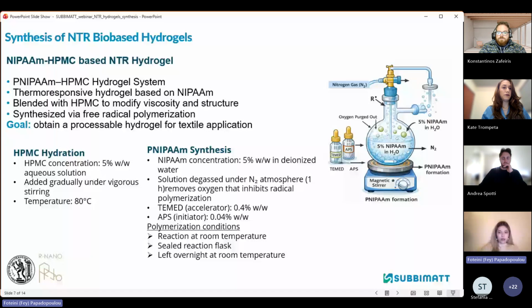Free radical polymerization forms the final network, and for this reason, we have APS as the initiator and TEMED as the accelerator. The initiator and the accelerator are vital because elevating the temperature above the NIPAM and HPMC transition temperature results in a collapsed polymer network that can't be further processed. So keeping the temperature low, room temperature ideally, or even lower, forms the NIPAM polymer, and mixing it with HPMC, we can actually make this hydrogel that looks like this.